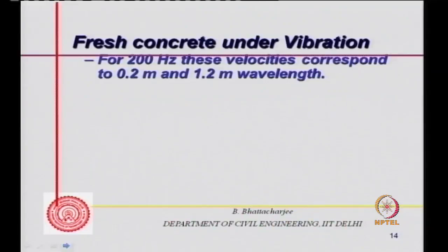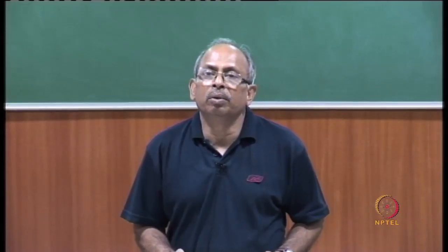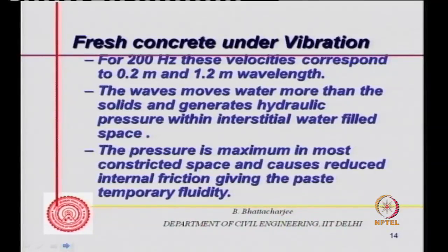For 200 hertz, the velocity corresponds to a wavelength of the order of around 0.2 meter to 1.2 meter. The waves move water more than the solids, that's what I was saying, and generate hydraulic pressure within the interstitial water-filled spaces. And this pressure is maximum in the most constricted space and causes reduced internal friction, giving the paste temporary fluidity.